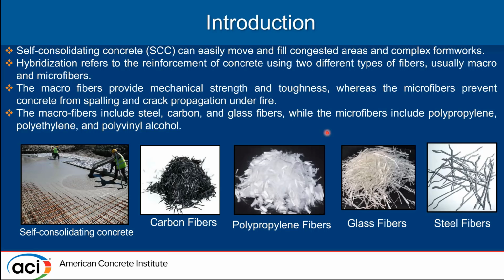Hybridization is a technique where concrete is reinforced using two different fiber types, basically the macrofibers and microfibers. So macrofibers are known to provide mechanical strength and toughness to the concrete matrix, while the microfibers help in reduction of crack propagations and also known to avoid fire spalling of the concrete. Typical examples of macrofibers are steel, carbon and glass fibers, whereas for microfibers, we have polypropylene, polyvinyl alcohol, and polyethylene.